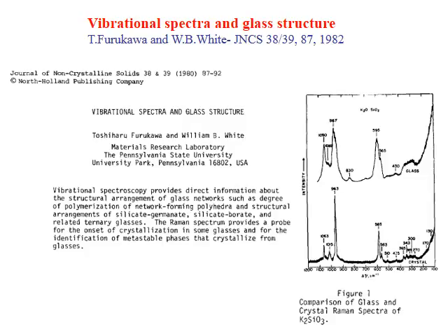In this paper from 1982, these authors presented vibrational spectra for glasses and crystalline counterparts. The figure shows Raman spectra obtained for potassium silicate, crystal and glass. Bands appear broadened for the glass, but at about the same positions of the bands observed for the crystal. The observation suggests similarities for crystal and glass structures. One can therefore take the crystal structure as initial point in the description of the glass structure. This is very useful, for example, in generating a glass structure by methods like molecular dynamics.